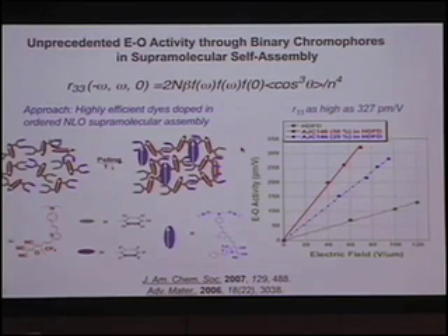So from reviewing this equation, you can see that in order to really increase the r33 number, you simultaneously increase the number density, beta, and also cosine cubed theta. We can achieve the poling-induced efficiency by utilizing self-assembling approaches. However, when we take another much more active molecule, indicated by this blue arrow, you can dope it into this lattice. When I organize that, this blue arrow will be organized along this ordered lattice. As a result, you can see that this gives you r33 as high as 327 picometers per volt.